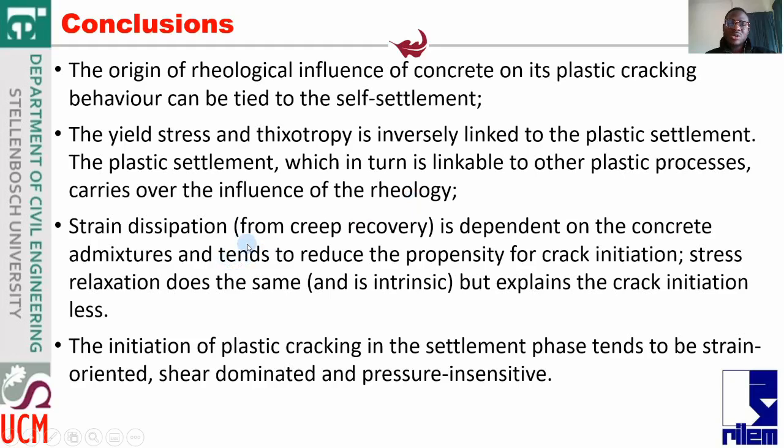And also that from the creep recovery, strain dissipation is dependent on concrete admixtures and tends to reduce the propensity for crack initiation. Stress relaxation, on the other hand, is intrinsic but explains less the crack initiation of plastic concrete. Also, that the initiation of plastic cracking in the settlement phase tends to be strain oriented, shear dominated, and pressure insensitive.